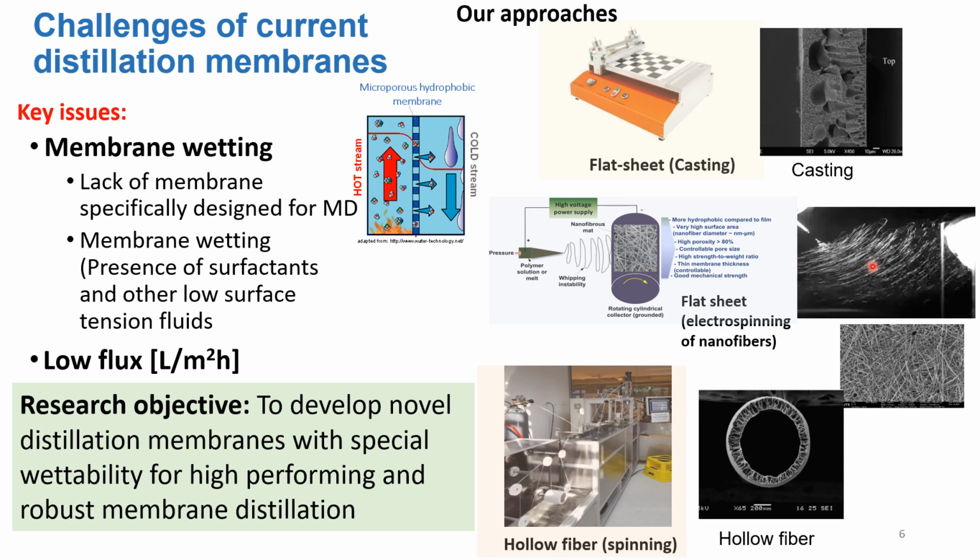And if you can see from here, you can see a lot of nanofibers being emitted, coming out from a nozzle and collected on the other side, at the collector. The collector collects the membrane. In this case, it is somewhat considered a layer by layer deposition of membrane, so it can be considered a form of 3D printing technology. But you can control various parameters, like material parameters or process parameters, so that you can control the various porosities, pore sizes, thickness, as well as the surface functionalization of the membranes. I will talk more about this in the later slides.